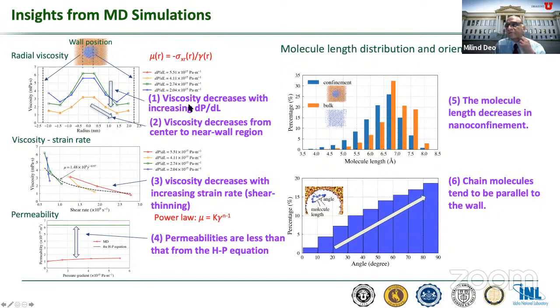And here the focus was more on viscosity behavior, because there is another factor to the change in physical laws under confinement, and that is viscosity. So we don't know if the viscosity values that we are using, by the way, all of the viscosity values that I showed you during the comparisons between continuum and confined flow were bulk values. So bulk viscosity values were adjusted for pressure, but they were still bulk viscosity values. And we are also very deeply interested in trying to figure out what happens to viscosity under confinement.